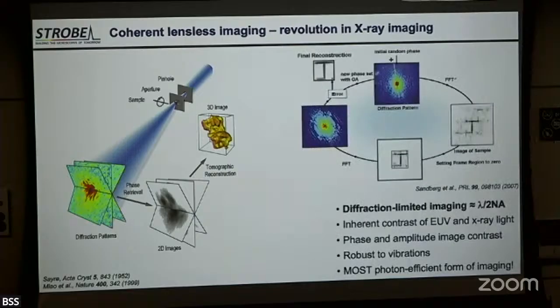So how does it work? How do these algorithms work? Well, initially they didn't work very well, and in fact it wasn't a viable imaging technique, because initially the algorithms and compute power were much limited. So what we did initially was, for example, a little hole in a piece of metal. You shine the UV beam on it, get a scatter pattern. You need to do a Fourier transform, but you have no idea what the phase is.